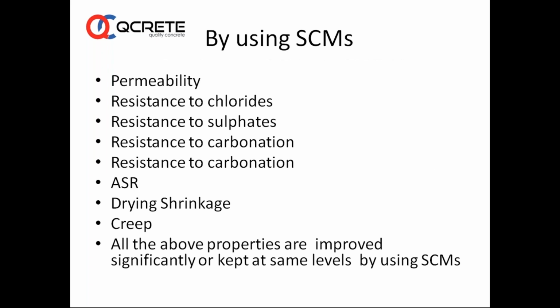So by using SCMs, what are the benefits that you get to make it overall durable? Permeability, resistance to chlorides, resistance to sulfates, carbonation, alkali silica reactivity, drying shrinkage, creep. All the above properties are improved significantly or kept at the same levels by using SCMs. Some of the parameters of durability are at the same level, whereas many of the important properties are enhanced significantly, especially permeability, resistance to chloride and sulfates. All these are enhanced significantly when we are using SCMs, by which the SCMs push the concrete to a higher degree of durability.